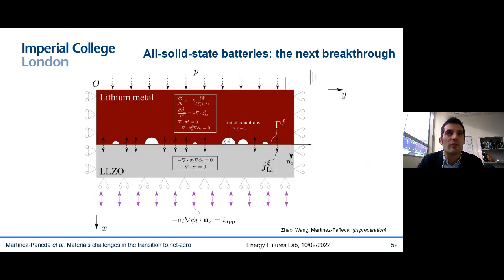So we solve a diffusion problem. We solve a phase field voiding problem. So we use the phase field to predict how the voids evolve. We solve a mechanical viscoplasticity problem for the lithium metal. And then we solve also an electric problem. And we model both the anode and the electrolyte. And we try to gain insight into voiding and the emergence of hotspots as a function of the applied pressure. So it has been argued for a long time that solid state batteries can become viable if we apply a pressure to them, and also as a function of charge and material properties, of course.